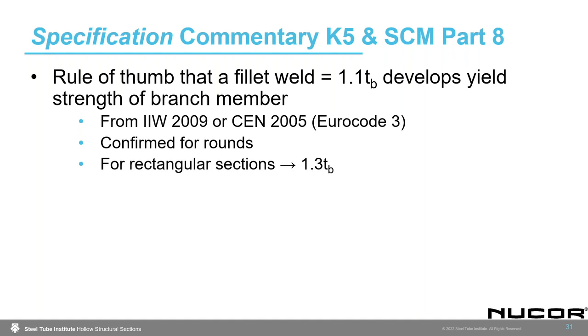However, for rectangular sections, it actually looks like that factor should be more like 1.3 rather than 1.1. This is just a rule of thumb, it's not codified, but if you are using this rule of thumb or have used it in the past, that's something you might want to take a look at and confirm if you're using that rule of thumb for rectangular sections. Again, hopefully we're not developing the yield strength of a branch member on a regular basis. We're designing for the actual applied loads.